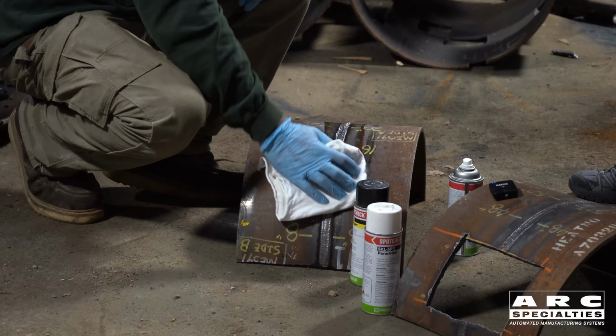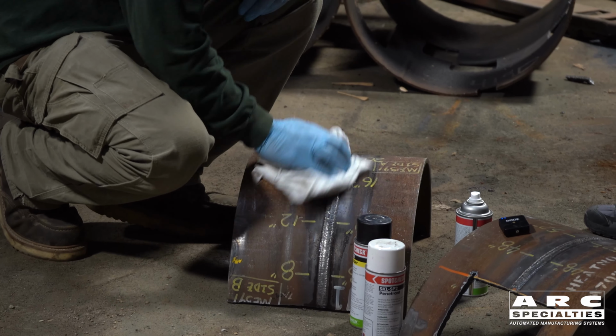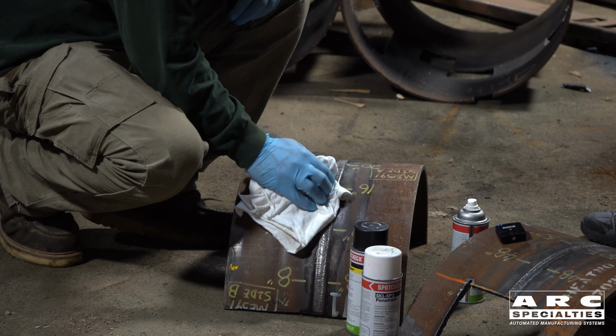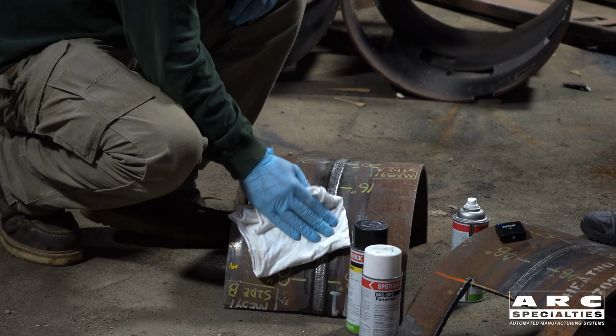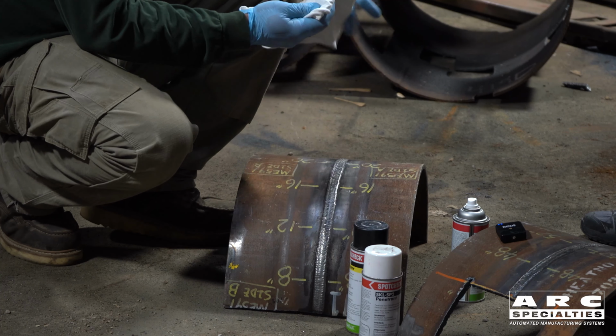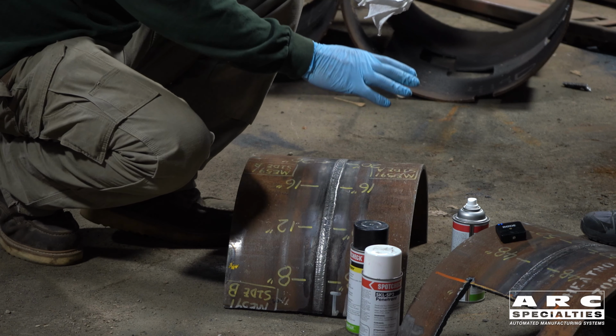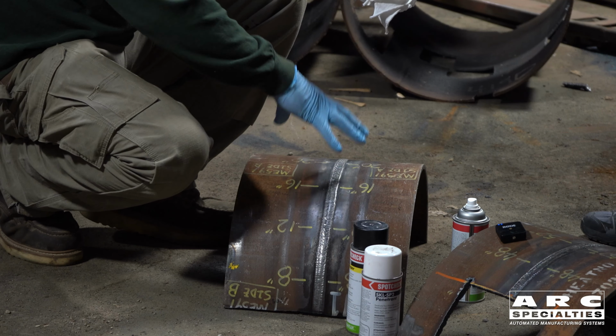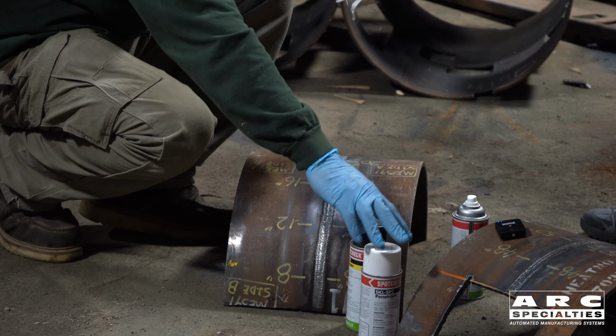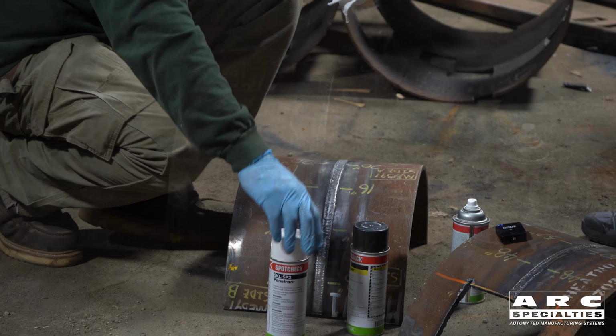Spray your cleaner on. You wipe it down and make sure you get the toe of the weld good and clean. Make sure there's no slag or anything like that on the weld. And now we have to set for 10 minutes and let that evaporate completely before we can add our penetrant.